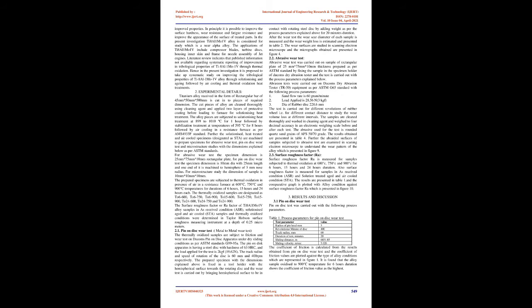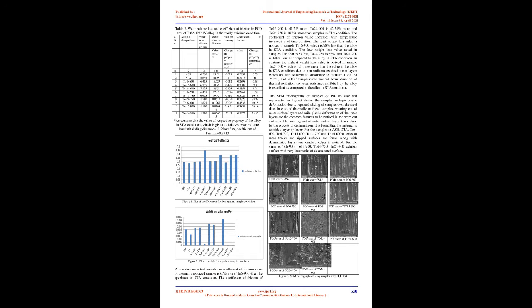Many non-metallic elements are used to enhance the titanium alloy surface to improve its tribological properties, which can form a hardened, interstitially enriched alpha case layer with or without an outer surface layer of hard compound. Thermal oxidation is one of the widely used thermochemical treatments for titanium alloys. In the process, oxygen is incorporated into the surface layers of titanium base alloys at elevated temperatures and yields various combinations of improved properties. In principle, it is possible to improve the surface hardness, wear resistance, and fatigue resistance and improve the appearance of the surface of treated parts.